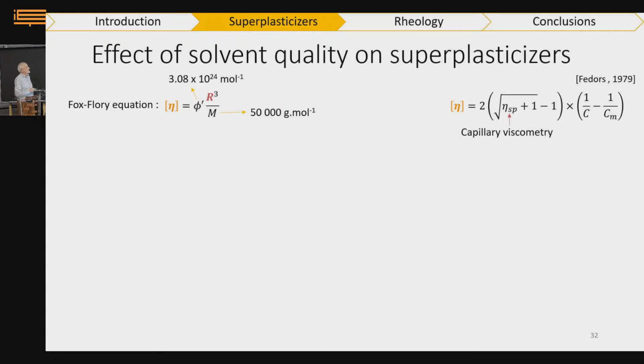What's important is that we can measure the intrinsic viscosity of our solution, whatever the composition of the solution, and we can relate it to the radius of the blobs formed by the polymer in solution. So we have a very simple way, without going to neutron scattering, to appreciate how the radius evolves in solution, and this is relatively sensitive because it is to the cube, by simply measuring the intrinsic viscosity of the solution with the capillary viscometer.